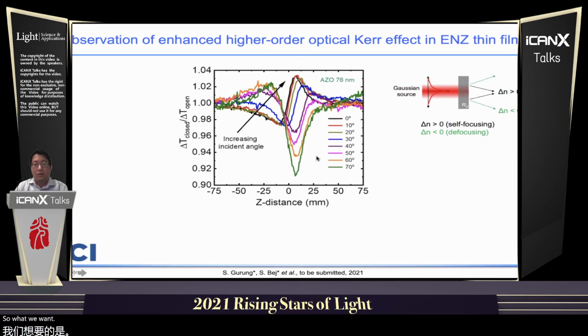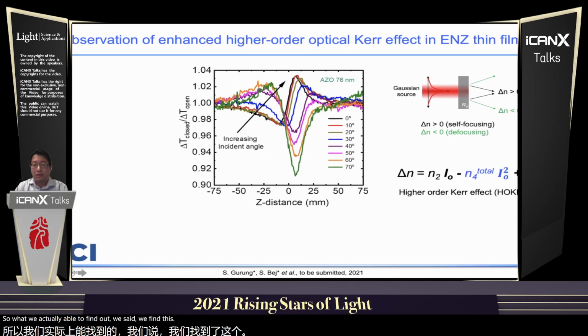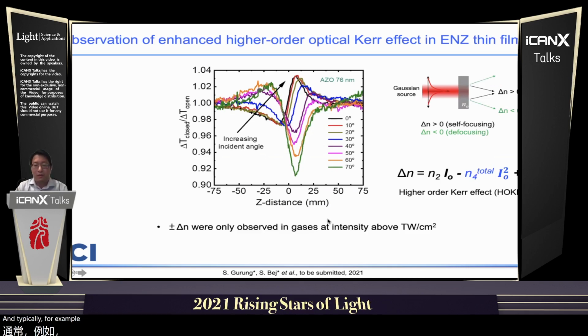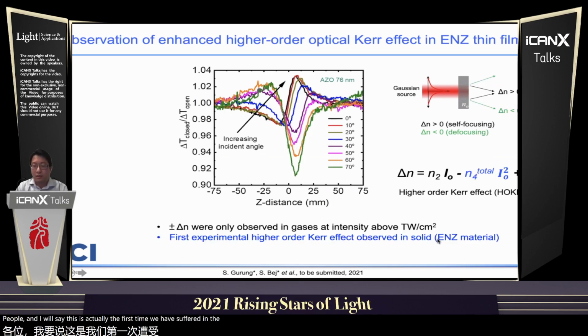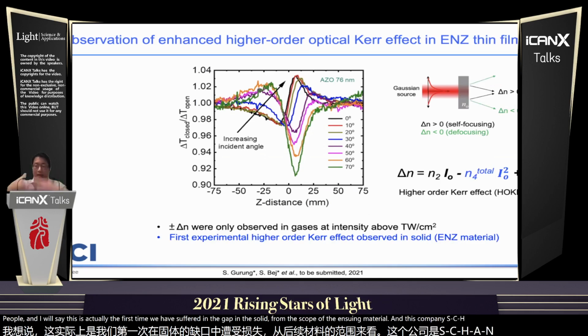So what we are able to find out is that there's quite an interesting contribution from the higher order Kerr nonlinearity, for example, N4. And in this kind of ENZ material, it further enhances this N4 contribution. Typically, people have observed this kind of high order Kerr effect in gases at really high peak power. And I would say this is the first time we observe it in a solid, in this kind of ENZ material. This ENZ significantly enhances the high order term, which induces this change of sign of the nonlinearity here. So this is quite exciting.